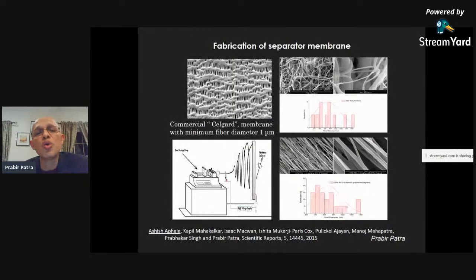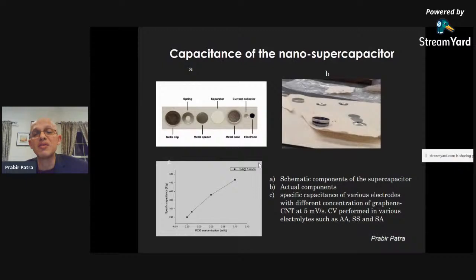And then what we did is, in a supercapacitor device, you need electrodes, you need a separator, and then you have contact electrodes, right? So the separator we also made ourselves. We didn't take commercially available Celgard, but compared with it. Normally what you do is we take our aligned fibers, as you see in the middle picture, and then wrap some filter paper with it, and soak it in sodium chloride and put it in as a membrane separator in the supercapacitor device.